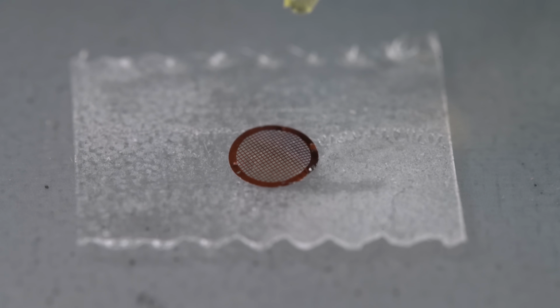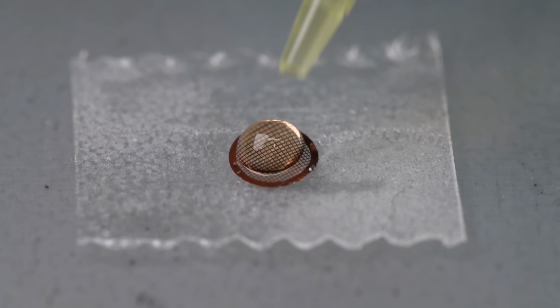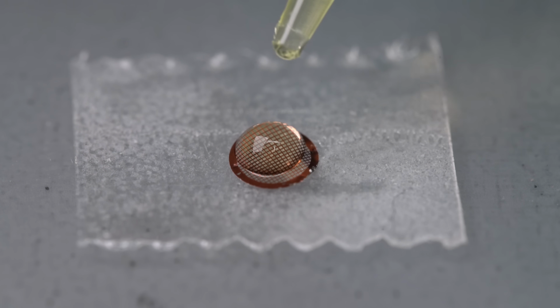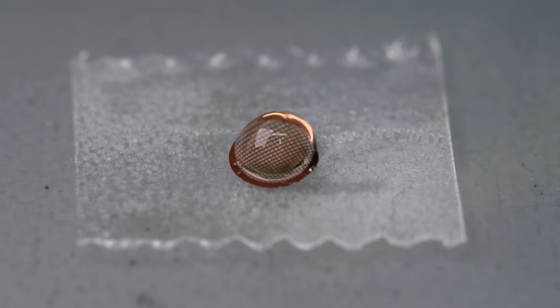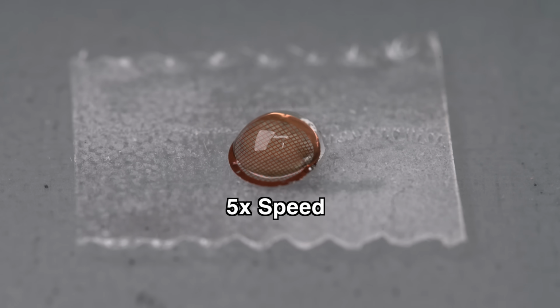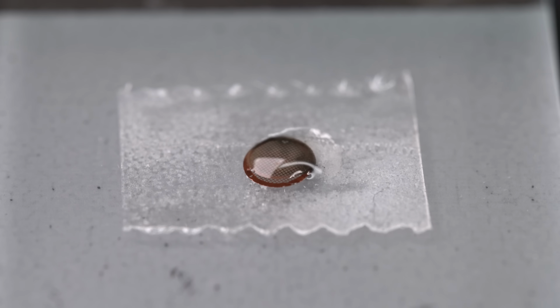surface. I start by adding 10 microliters of a chloroauric acid solution on the surface of the grid. To that, I add 10 microliters of a sodium metabisulfite solution. This causes a chemical reaction where the gold comes out of solution and forms tiny spheres, or nanoparticles. Nanoparticles below 100 nanometers in size can generally remain suspended in solution, but the ones I'm making here are large enough that they should settle to the bottom. Alright, the reaction seems to be finished.